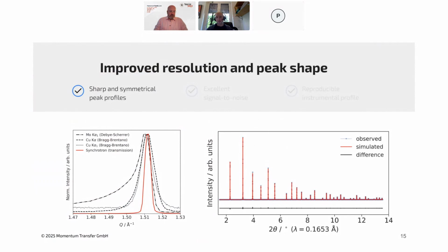So from this setup, we can get very high resolution data. And if you compare a typical diffraction peak from a highly crystalline material from our setup to typical lab devices, you can see that the line profile is a lot thinner, but it's also much more symmetric than a lot of laboratory devices. Part of the reason for that is, and you see in this signal from molybdenum K alpha, there's this very significant asymmetric broadening towards the lower Q or lower angle part of the signal.